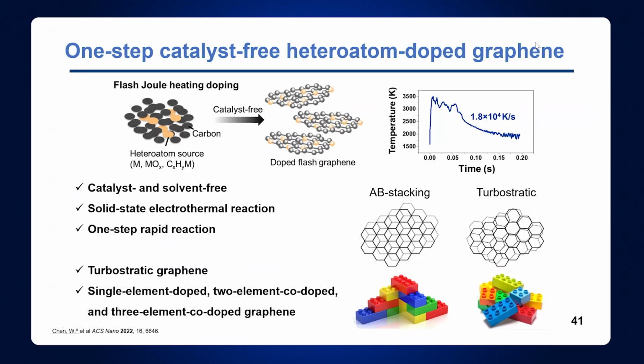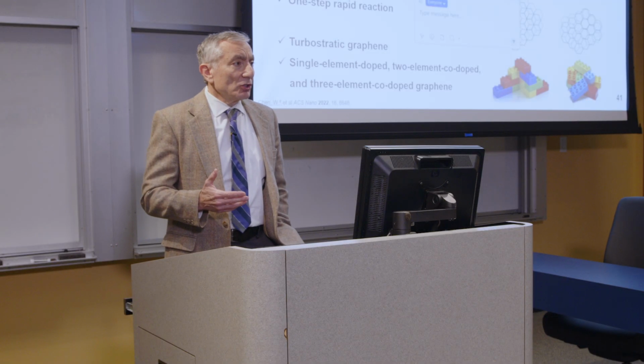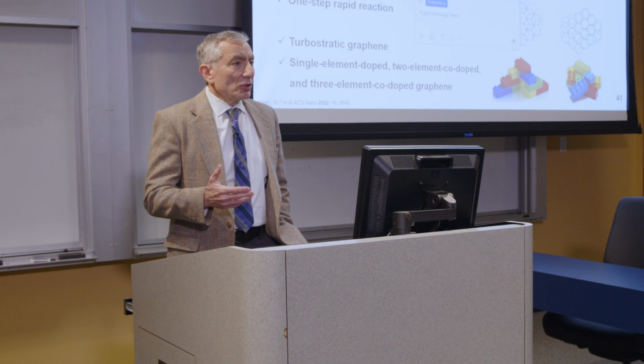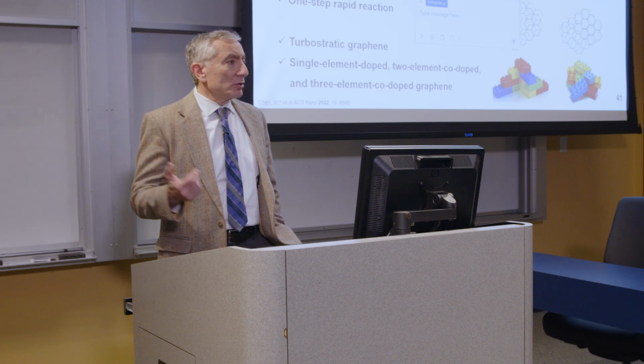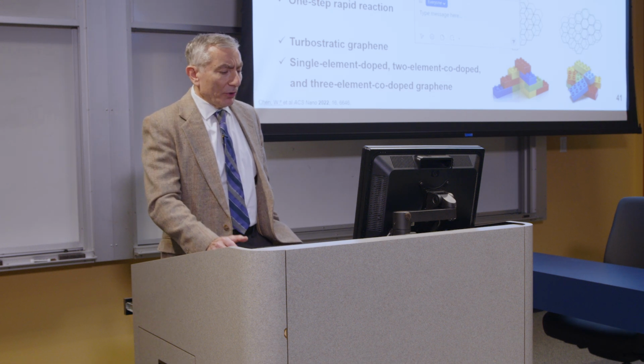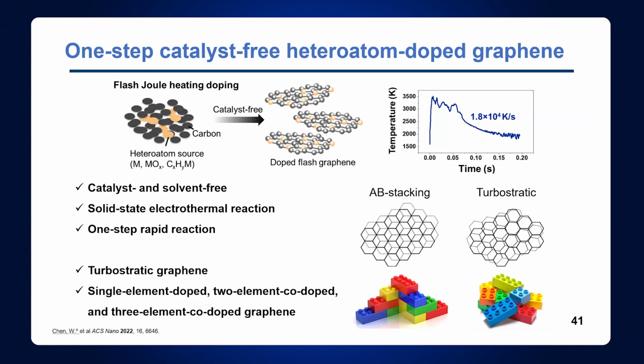Aluminum boils at about 2600 centigrade, silicon around the same temperature. Carbon doesn't boil until about 4400, and so 4200, somewhere in there. So you can distill out all of those other heteroatoms, many of the other heteroatoms. Now, there are some things that wouldn't come out, but most of what you would ever find in plastic is going to come out. So it's self-purifying in that flash process. It's an amazing process. I mean, there's very few things like that.